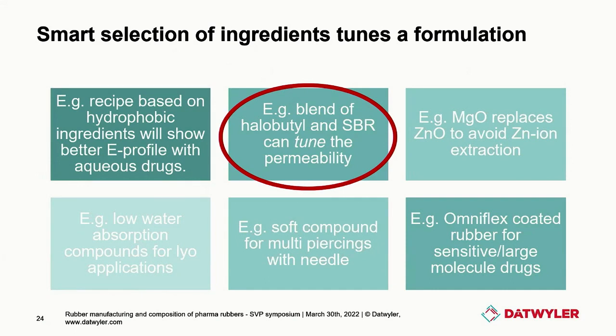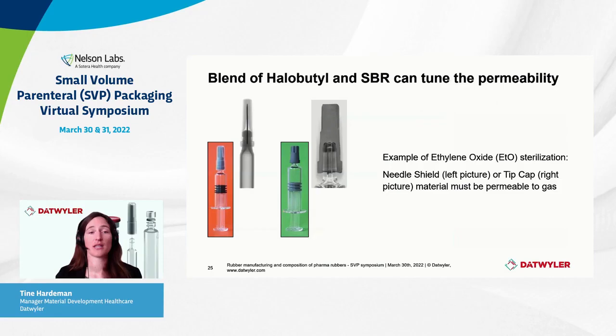So if you want a compound that has a higher gas permeability, you can, for example, include some SBR into a halobutyl compound. This can, for example, be necessary when you want to have a formulation for tip caps or needle shields. If you want to enable ETO sterilization of the tip caps or needle shield on the barrel, you need to have a sufficiently high permeability to be able to really sterilize the entire area also around the needle here, for example. And you can achieve this by including SBR into the compound to have a sufficiently high permeability, for example.